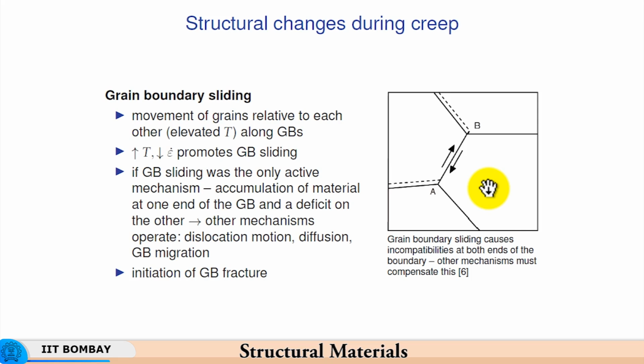So, there the creep rate is so low because the diffusion is very small, the diffusivity of atoms is extremely small, diffusivity of solutes through the crystal structure is extremely small. So, these are all body centered cubic materials, the refractory materials are usually body centered cubic, be it tungsten, be it molybdenum, and these materials permit very little diffusivity through the lattice. And so, any mechanism that requires diffusion, because if you have grain boundary sliding, you need diffusion to take place to bridge this deficit. So, the rate of diffusion becomes the rate controlling mechanism of how fast the grain boundaries can slide, to what extent the grain boundaries can possibly slide.